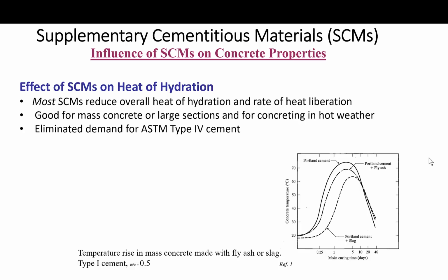So let me just say the following: mineral admixtures reduce the overall heat of hydration, and in particular the rate of heat liberation, which controls the temperature rise in hardening concrete. The use of a mineral admixture is equivalent to raising the C2S content of a cement, and effectively turns type 1 cement into type 2 or type 4 cement by doing that.